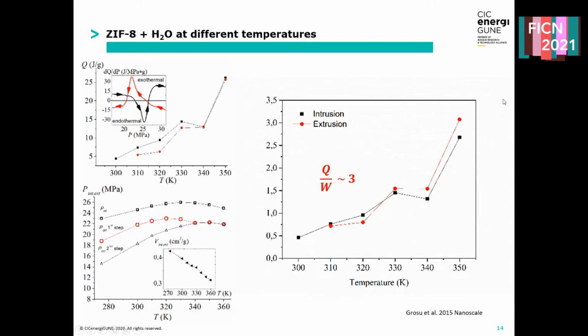What is essential here is the heat in this process, because this comes from the environment. So we are using environmental heat, and we would like to use as much of it as possible. Some of the systems actually demonstrate that the contribution of heat can be much greater than the work in the system. In this example, for ZIF-8 metal-organic framework and water during the intrusion-extrusion, the generated heat increases a lot with temperature, especially if we increase the temperature of the experiment a bit, while the mechanical work not so much. It stays more or less constant with temperature, and this results in the fact that at a bit higher temperatures, the amount of heat absorbed in the system is around 3 times as compared to the work supplied to the system.